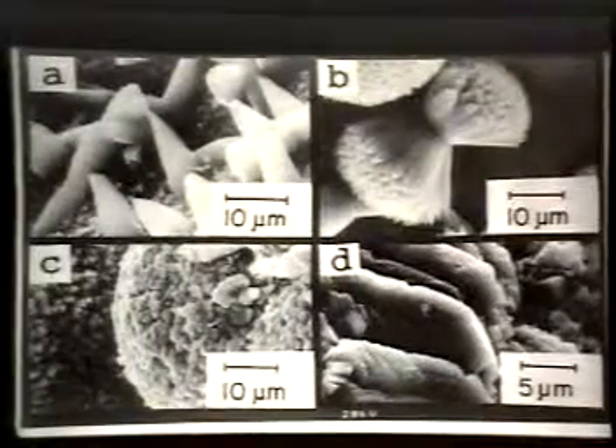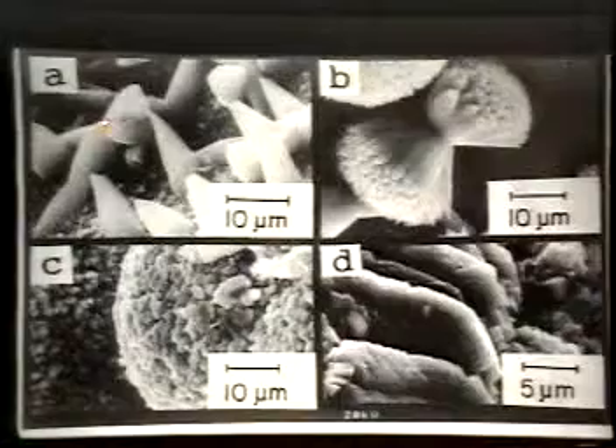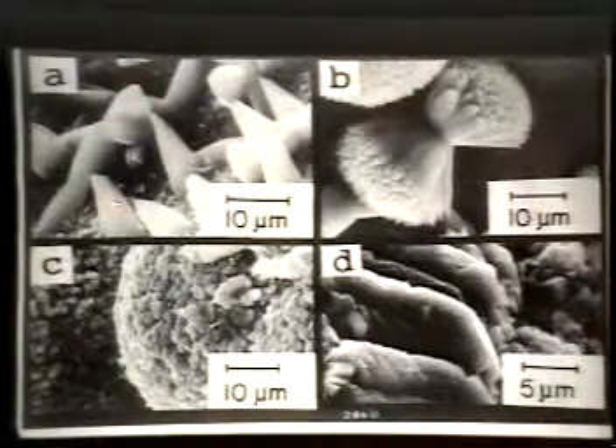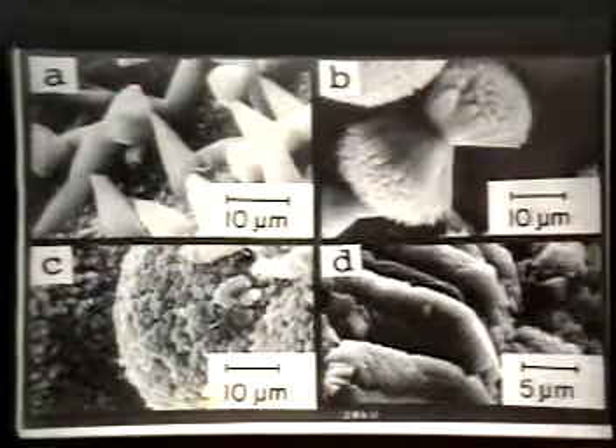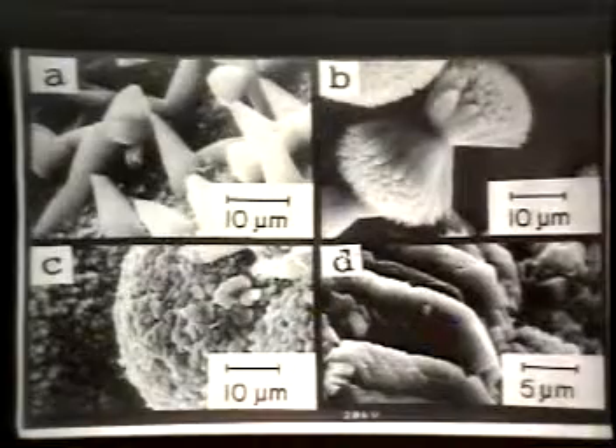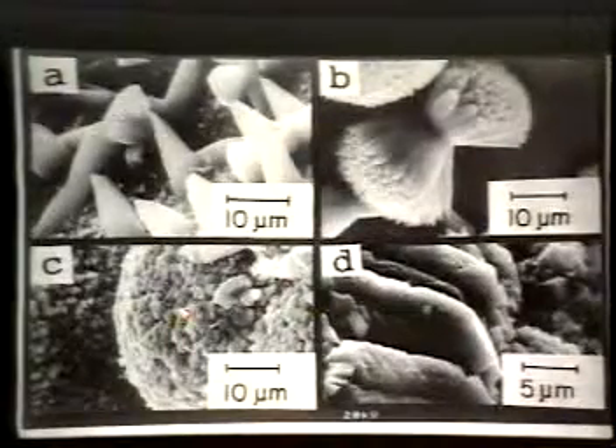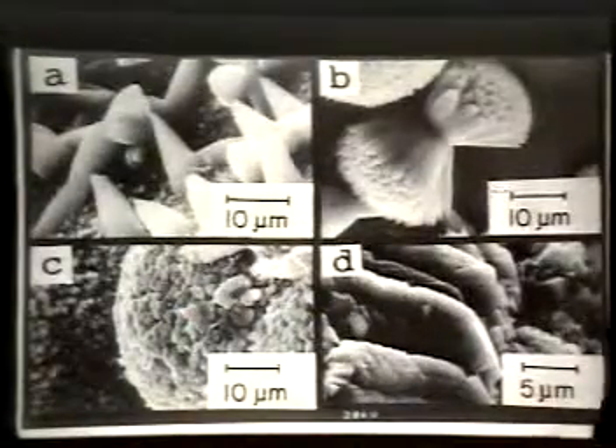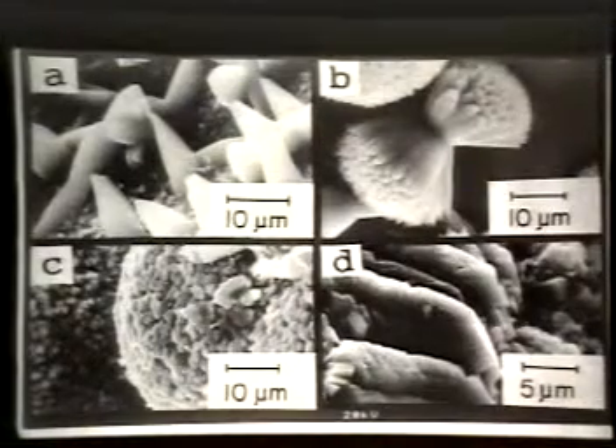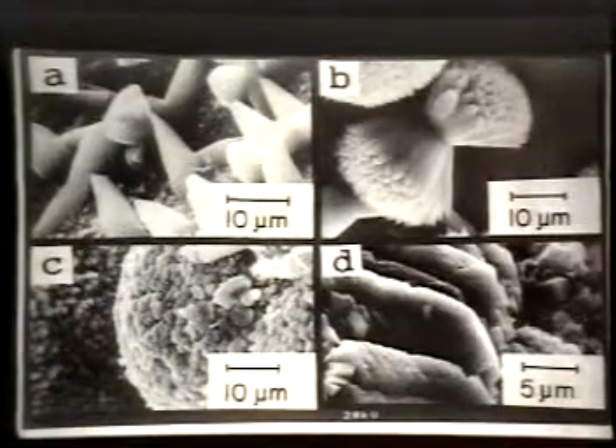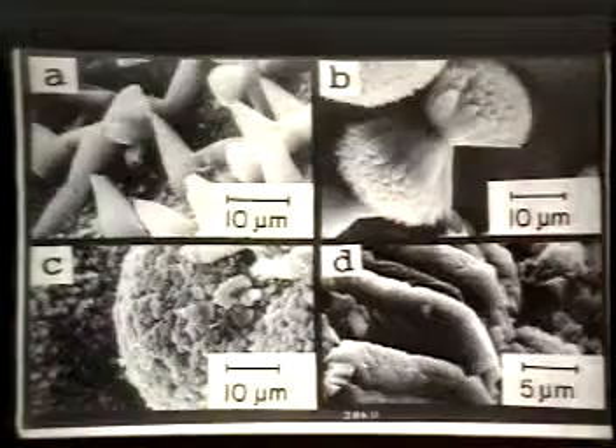When you look at these carbonate crystals under the SEM, this is what they look like: dogtooth crystal, floral distribution, globular structure, and the stalactite. They're all calcium carbonate, formed under different conditions at different times. But this is what you see in the concrete. Next, please.